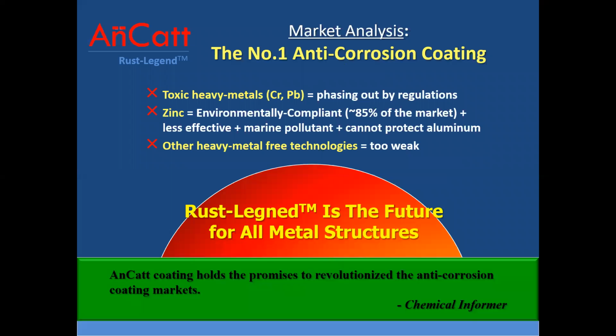With highly toxic heavy metals such as chromium and lead facing bans by regulations, zinc is the only environmentally compliant anti-corrosion pigment, accounting for 85% of the current market, but it is less effective, requires more frequent repainting, and it's still a marine pollutant that kills fish and marine animals. It is prohibited in ports and certain open waters, and it cannot protect aluminum, which is a major aviation material. Other heavy metal-free technologies are too weak in performance, not even reaching the minimum high-performance anti-corrosion coating requirement of 1,000 hours of independent corrosion tests.